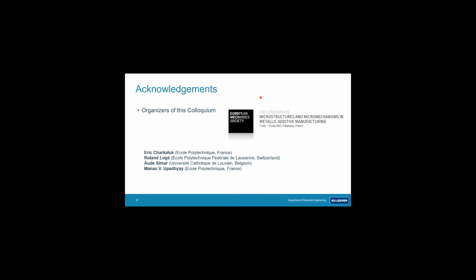I see that Roland has raised his hand. Yes, Roland? Thank you. Thanks a lot, Kim. Very interesting. We have been working also on highly reflective materials, more like gold alloys. I was just wondering, at the beginning, you showed that when you really deal with the pure copper, you actually need to go in the keyhole mode to be able to really process it well. But it's very close to the transition with the conduction mode. And then you mentioned what goes on the liquid and on the powder, which I also discussed a bit yesterday. I was wondering if you try to change very much the combination of power and velocity, because that can have an influence on the part of the laser beam that goes on the liquid and on the powder. And the more you go on the powder, the better it is. And this might help moving maybe a little bit towards the conduction modes.